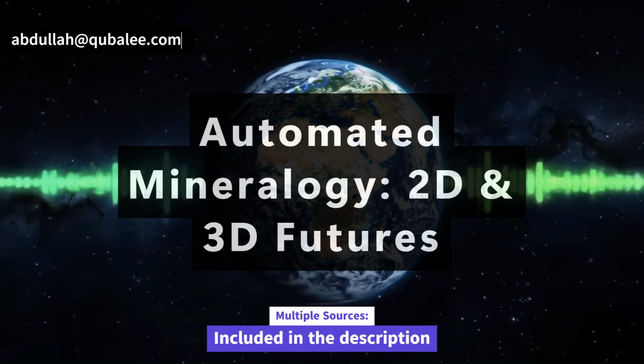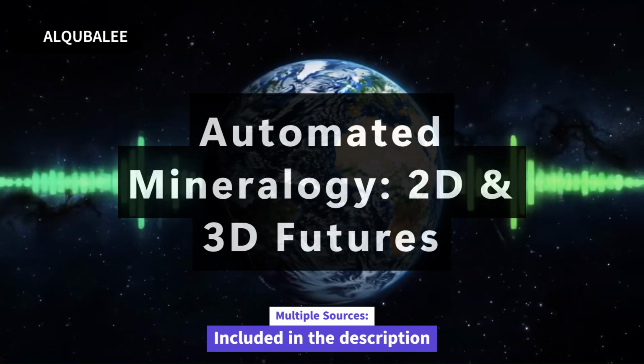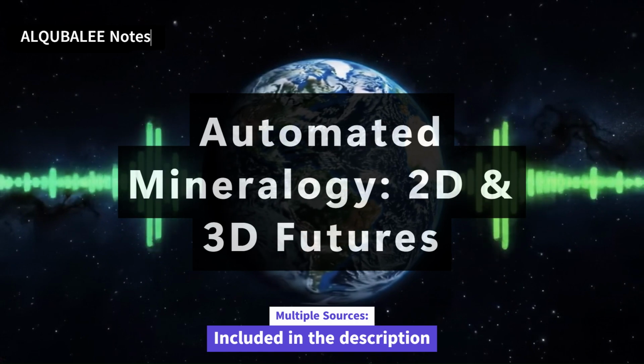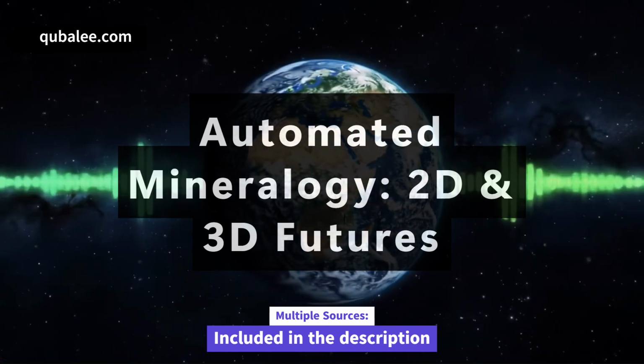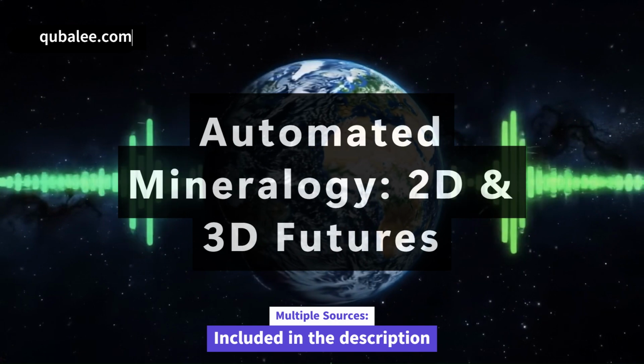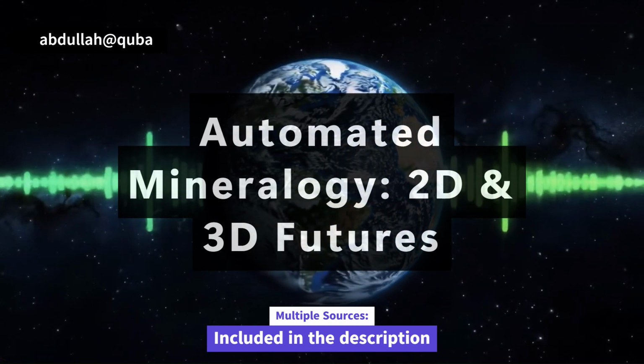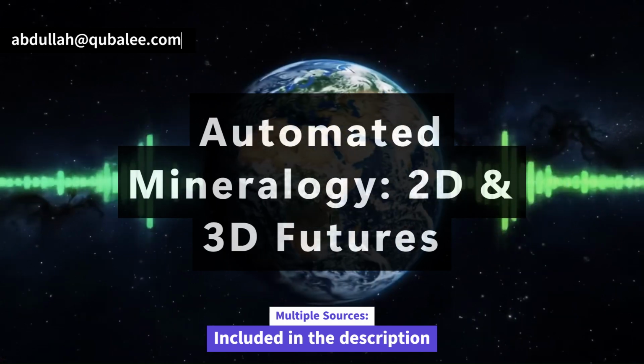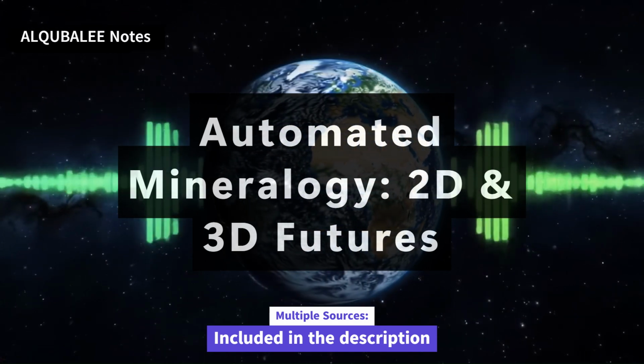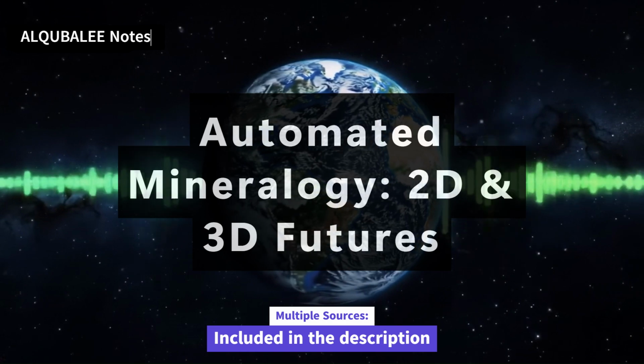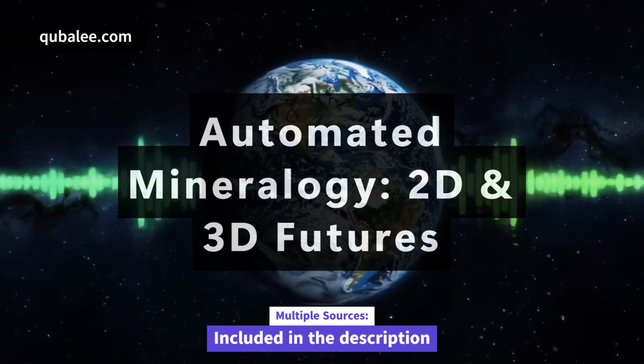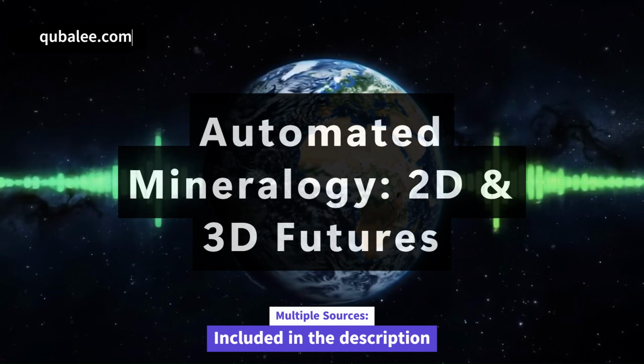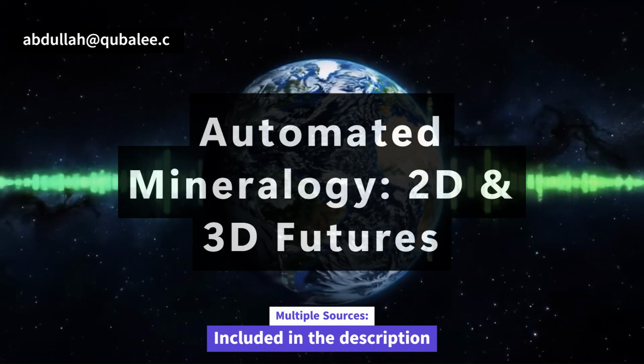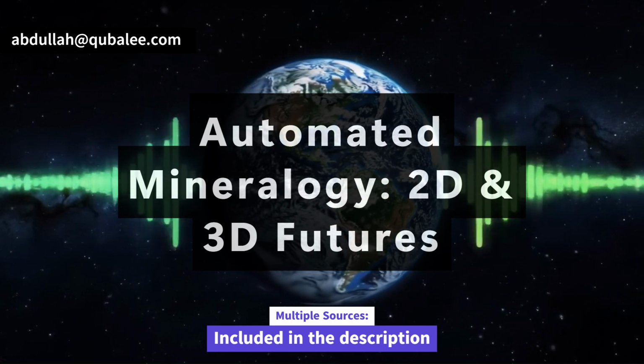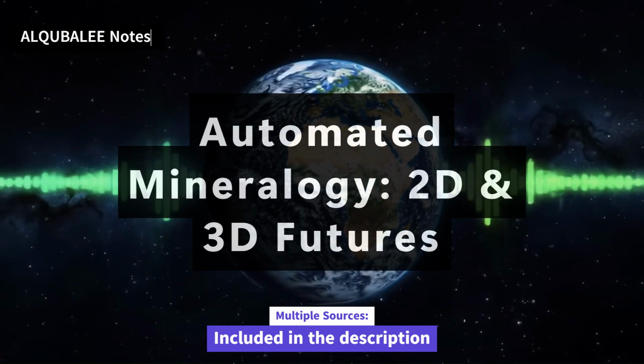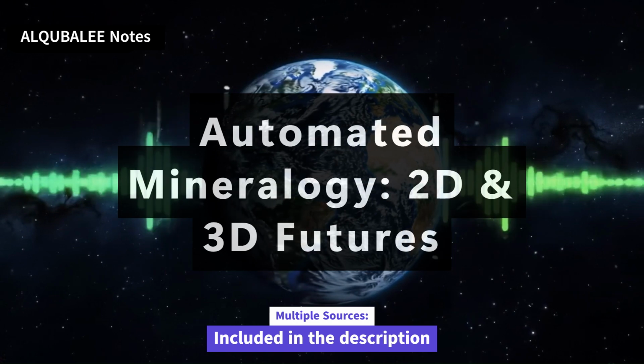And this is where the automated part and the software really become critical. Absolutely. The real magic, or maybe the real complexity, is in the software. It takes all those measured spectra, one for every pixel. Thousands. Millions. Yeah, millions potentially. And it automatically compares them against a huge library. This library has reference data, fingerprints for known minerals or standards, or even spectra generated synthetically from known chemistries. And based on how well they match, it decides, okay, this pixel is quartz or this one's pyrite. That's the core idea. It classifies the mineral at each pixel.